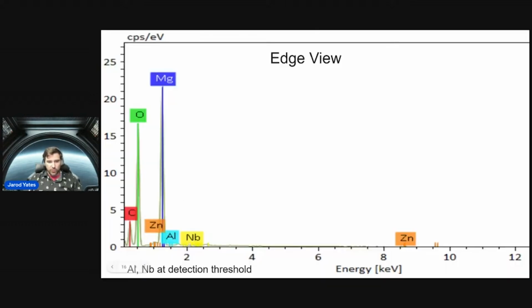Here is the rough spectra from that one. Now, important to keep in mind is when you're down here at the 1 to sub-1 keV range, anything where your count is below 1 is potentially noise. There might be something there, but it might also be a big old nothing burger. But right on the edge of that nothing burger, we were detecting some aluminum and niobium. This is the only time that we detected that, so it's likely noise. But at this point, with so many unknowns about this, it's important to keep in mind every single little thing that you are able to observe. The important part is we have magnesium and zinc, like we've been saying, and a fair bit of oxidation and carbonization on the edge here.